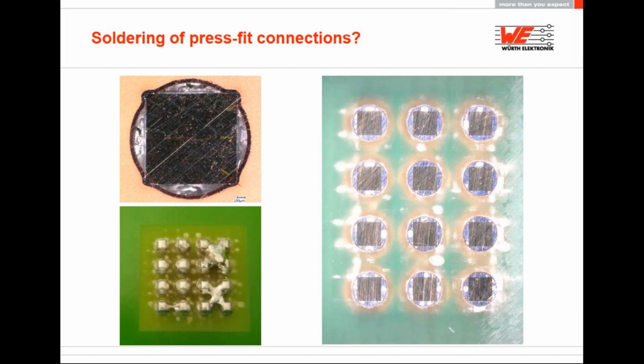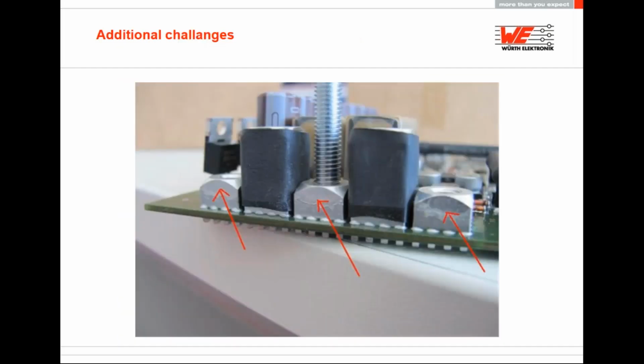Another thing is the process safety and verifiability. There's another issue with the heating effect, which is on the plating itself of the connector. The plating might be peeling away. Heating the REDCUBE press fit element can lead to thermal expansion, which weakens the press fit connection. It can also lead to melting of the tin surface, and the tin can accumulate in the thread and make it unusable.